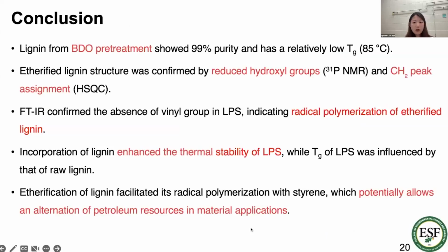To conclude this presentation, lignin from the BDO pretreatment showed very high purity, over 99%, and has a relatively lower glass transition temperature than the Kraft lignin. The etherified lignin structure was confirmed by the reduced hydroxyl group contents and the generated methylene group peak assignment through the HSQC. And once we prepared the copolymer, the FTIR confirmed the absence of the vinyl group in LPS, indicating the radical polymerization of etherified lignin and the styrene structure together.